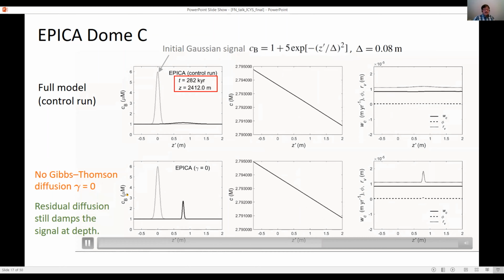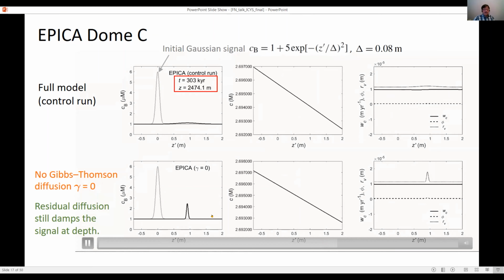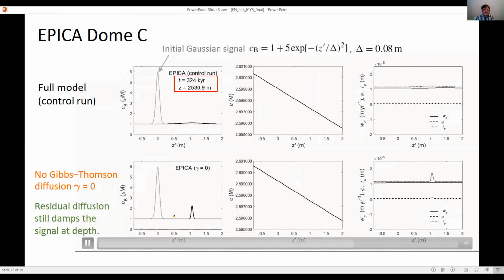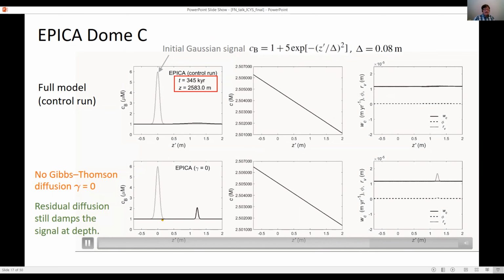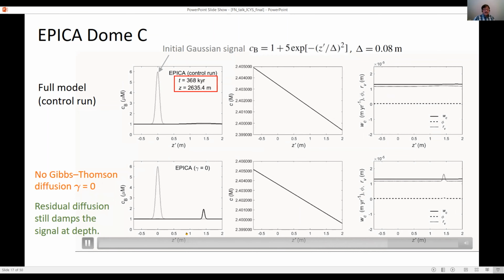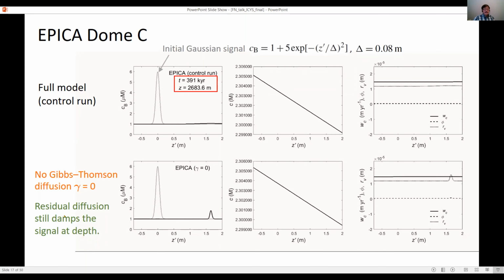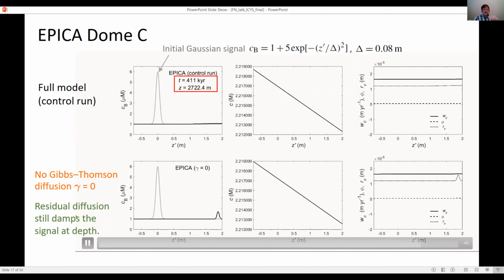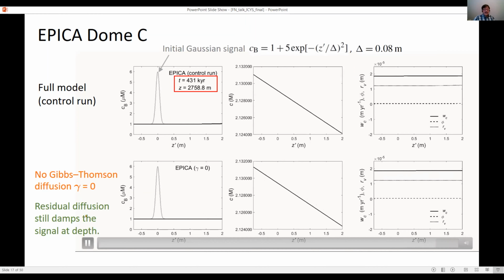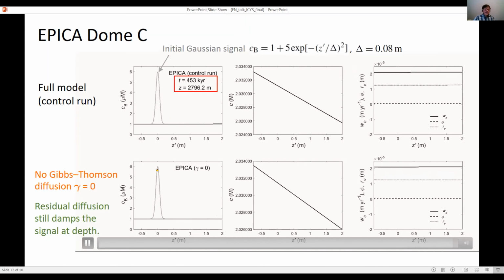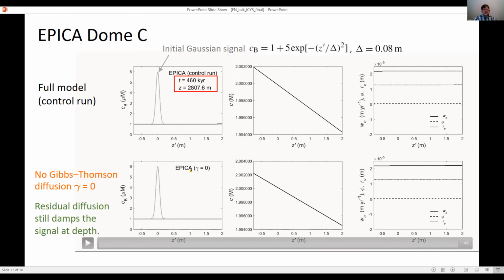When we switch off Gibbs-Thomson, really the same behavior. We have prolonged signal amplitude survival. A bit more of the signal is preserved for longer, but residual diffusion becomes important towards the bed in warm ice. Perfectly preserved signals just move along, narrowing with no change in amplitude.